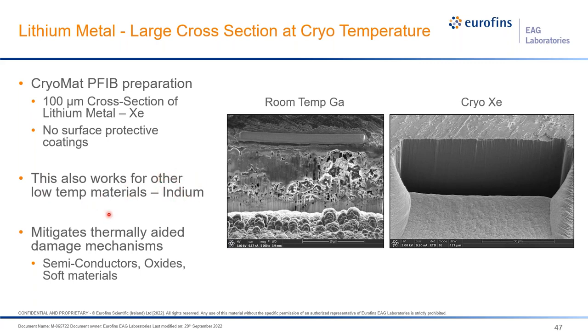And so this combination of non-gallium plus cryo really enables a new level of inspection of these kinds of sensitive materials. For the most part, we're going to utilize the cryo to mitigate the thermally aided damage mechanisms that you might find in semiconductors or oxides, as well as soft materials, and then also the non-gallium aspect. So you remove that sort of chemical aspect to the analysis as well. So creating very, very nice clean cross-section ability, seen here in lithium metal itself.